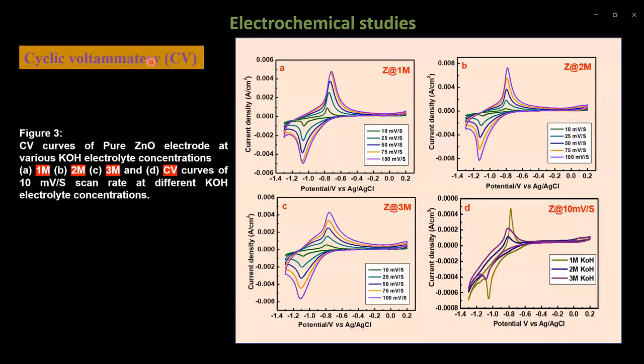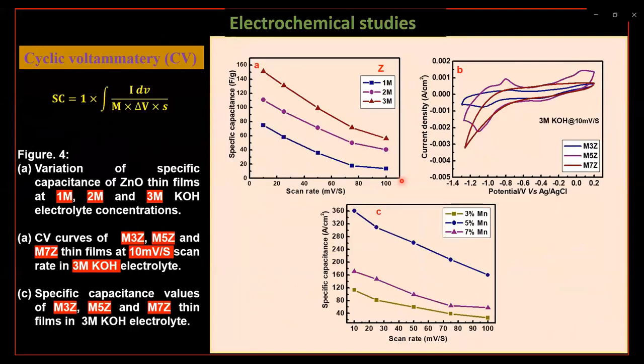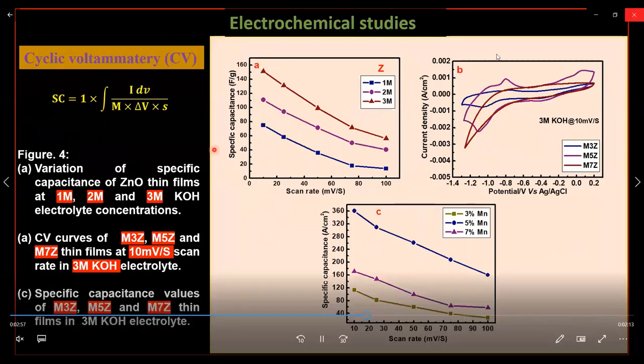Next characteristics is the electrochemical studies. First is cyclic voltammetry. This is the CV curve of the ZnO thin films or ZnO electrodes in 1 molar, 2 molar, and 3 molar. This is common for a 10 millivolt per second scan rate. The potential window used was minus 1.4 to 0.2. From this, specific capacitance was calculated with the help of this formula.